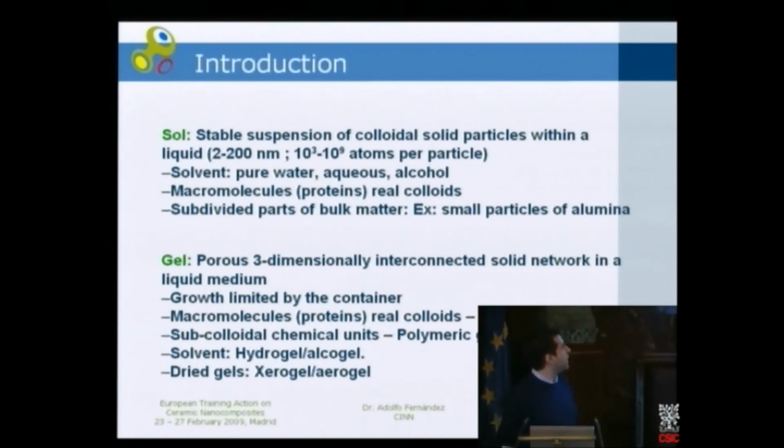Concerning gel, it is defined as a porous three-dimensional interconnected solid network in a liquid medium, and its growth is only limited by the container. If the macromolecules are real colloids, we are talking about a colloidal gel, and if it is a subcolloidal chemical unit, we are talking about a polymeric gel. And depending on the solvent used, we can divide in hydrogel or alcohol gel. And depending on the drying method, we talk about xerogel if it is a conventional heating for drying, or aerogel if it is a supercritical method.